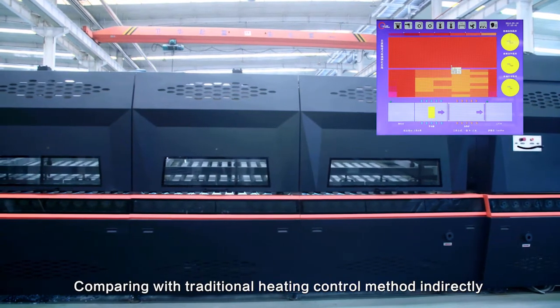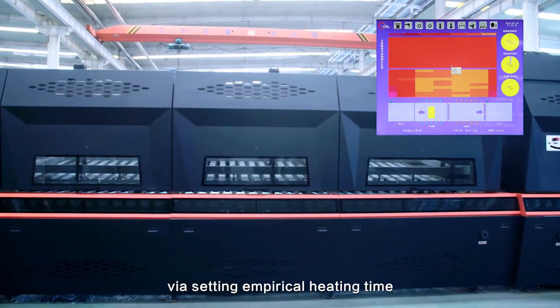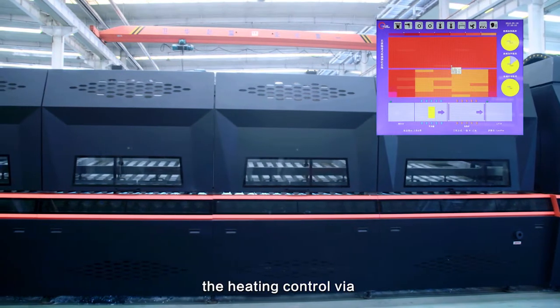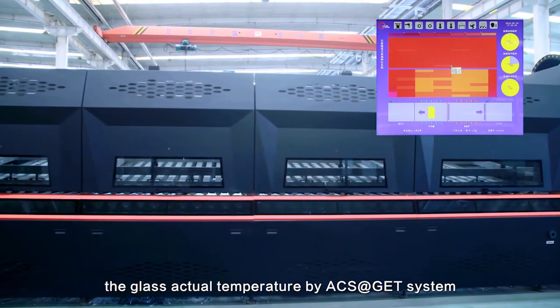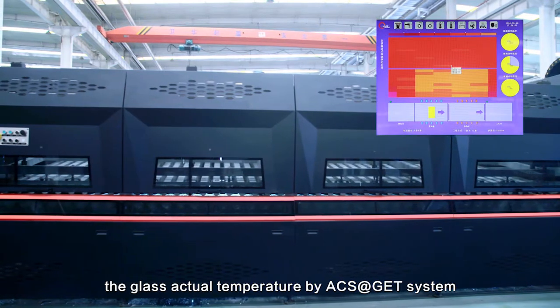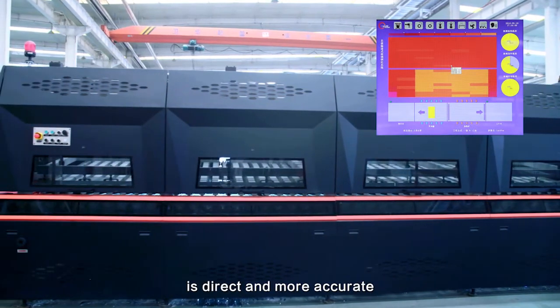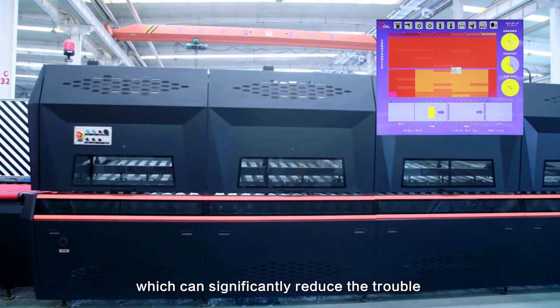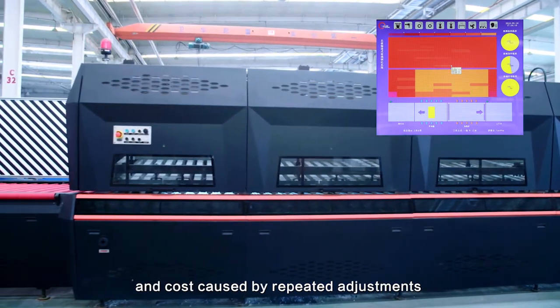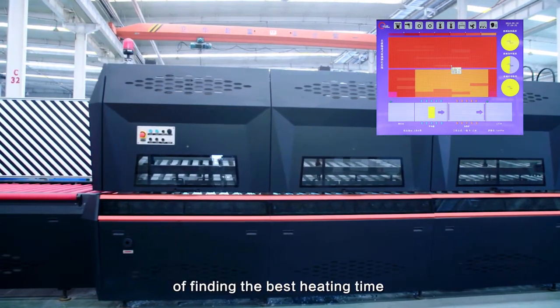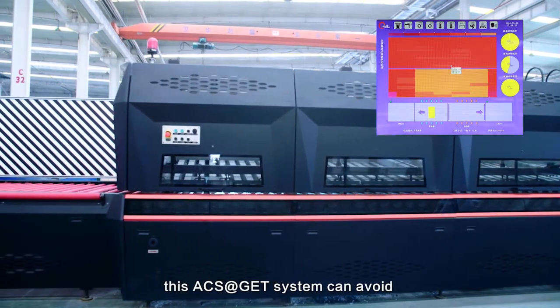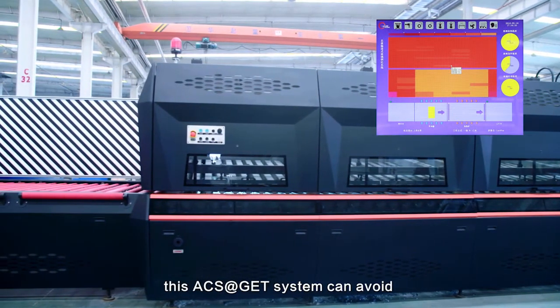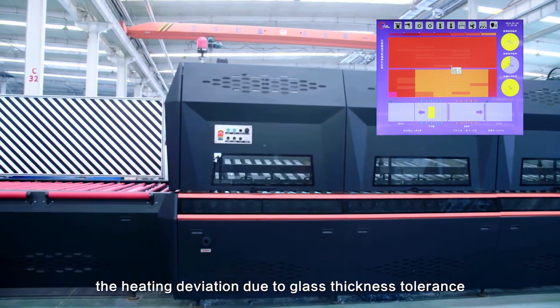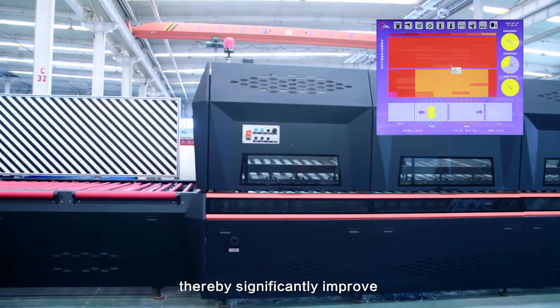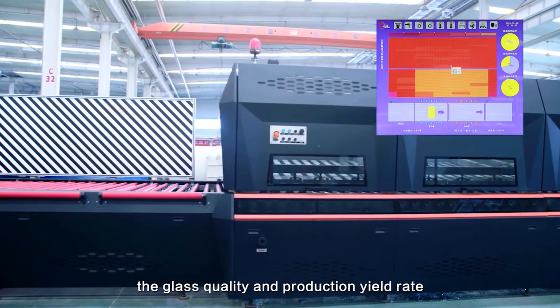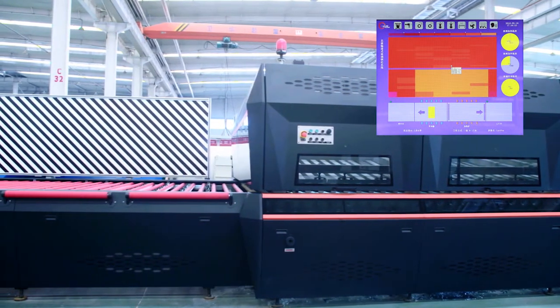Compared with the traditional heating control method, which works indirectly by setting an empirical heating time, the heating control via the glass actual temperature by the ACS at GET system is direct and more accurate, which can significantly reduce the trouble and cost caused by repeated adjustments to find the best heating time. More importantly, this ACS at GET system can avoid heating deviation due to glass thickness tolerance, thereby significantly improving the glass quality and production yield rate.